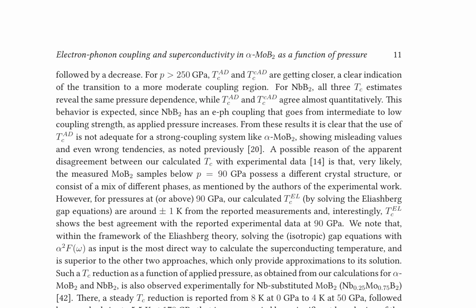The study investigates the lattice dynamical properties, electron-phonon coupling, and superconductivity of alpha MoB2 under pressures ranging from 70 gigapascals to 300 gigapascals. It reveals that the electron-phonon interaction leads to significant phonon linewidths along specific high-symmetry paths, particularly for the highest frequency optical phonon mode and low-frequency acoustic phonon modes. These modes contribute predominantly to the electron-phonon coupling constant.